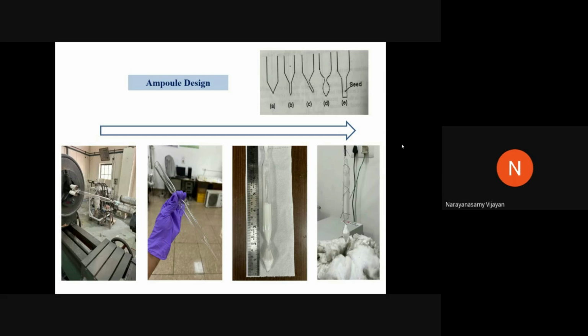Why do single crystals have more defects in melt growth in comparison with solution growth? Because in solution growth, I am not playing with high temperatures. In solution growth, I am playing with room temperatures, maximum going up to 30, 35. But in melt growth, we are going for high temperature materials, more than 1200 to 1300. After melting, you have to come back to room temperature. You can see the difference: more than 1200, 1300 degrees difference.